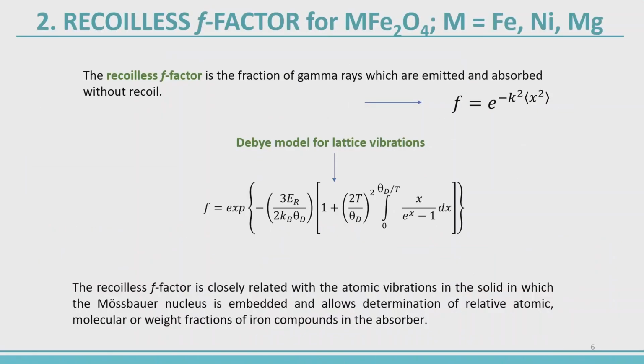So let's start first with one of the proposals that we have to determine the relative recoilless F factor. Remember that this is the general expression, but if we use the Debye model for lattice vibration, this is the expression here. I just want to point out that the recoilless F factor is important to us because we can determine the relative atomic molecular weight fractions of iron compounds in the absorber. That is the reason we want to determine the F factor.